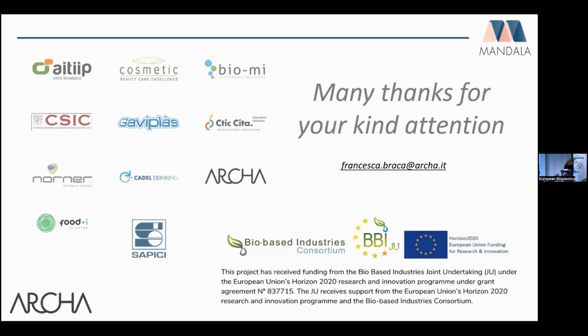For the biodegradability, I can say it depends on the material. It is not in our possibility to decrease the timing. We are at 80%. We can see that the graph is still increasing. If we have not yet reached the plateau, we still need 1 month, 2 months, 3, but I cannot be sure. So maybe with the final report published of this project, we will get some more insights, like in autumn. As I said to the partners involved in this project, we will go on even if the project finishes at the end of May, since the test started 1 year ago, but this test needs a lot of patience. Time, yes. We cannot be faster than what the material needs.